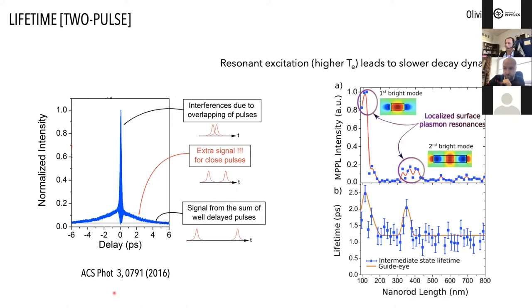We did this experiment back in 2016. So here you take a two pulse experiment, okay? And then you record this nonlinear photoluminescence as a function of delay between the two pulses. So you can see what's interesting here is this decay. The first part is basically intra-pulse interference when the two pulses perfectly overlap onto your sample.